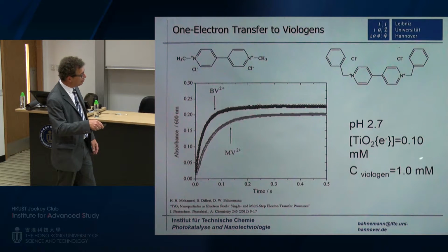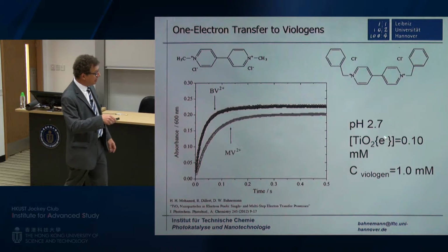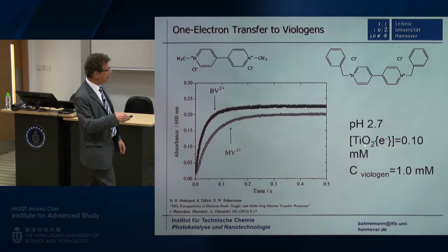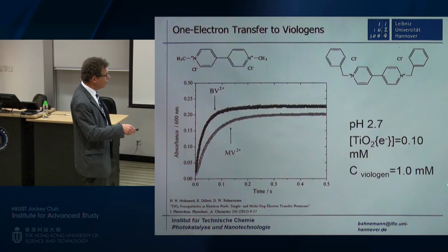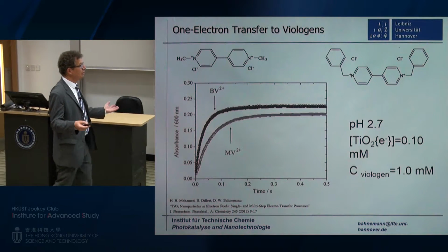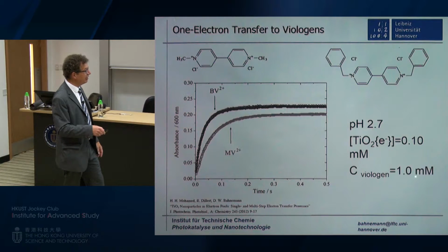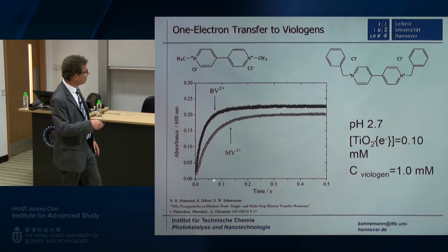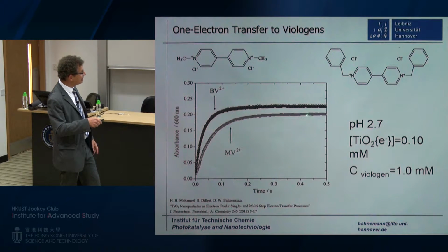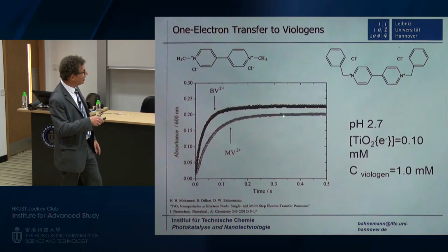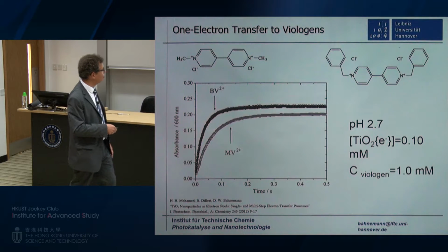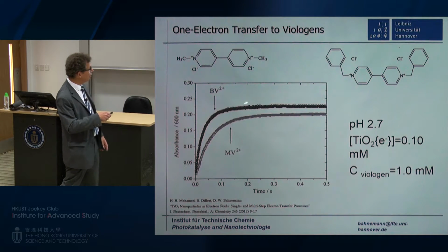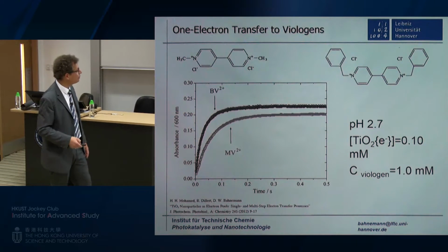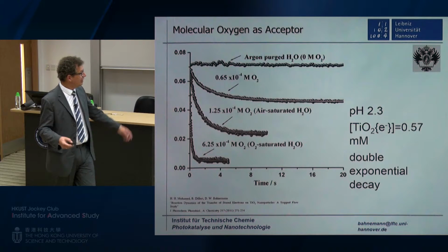In this case, we mixed 0.10 millimolar of electrons that we pre-illuminated in our TiO2 system with the viologen. This experiment is done in the dark with stopped-flow technique, and you can see how the signal of the radical cation goes up. This is for methylviologen and this is for benzylviologen, and you see the reaction with benzylviologen is a little bit faster than the one with methylviologen.